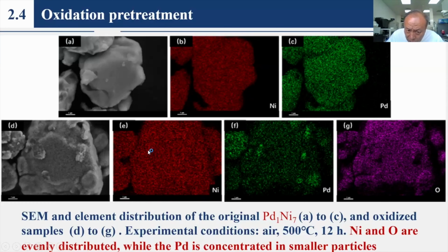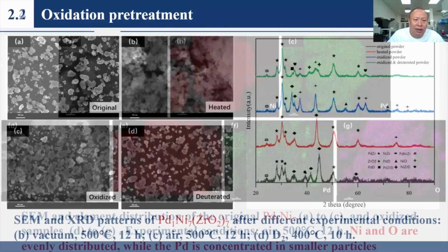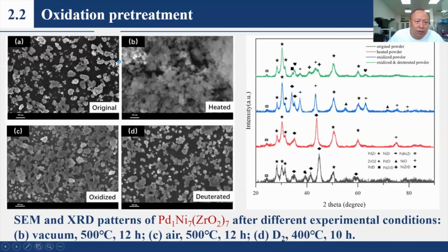We can find that after oxidation, the nickel and the oxygen are distributed evenly. However, the palladium is concentrated in smaller particles. Another is the oxidation of the PNZ sample. A, B, C, D are, respectively, the original, heated in vacuum, oxidized in air, and deuterated afterwards. We can find after heating, the grain size becomes larger. After oxidation, the grain size also grows larger. But after deuterated treatment, the grain size becomes smaller.